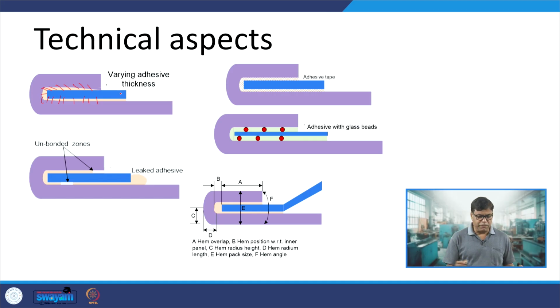And normally, when hemming is done, the adhesive thickness is difficult to control. In hem flange bonding, it is difficult to control the thickness of adhesive, because somewhere it is thin and somewhere it is thick. So, this reduces the mechanical performance. Therefore, a few approaches have been developed, like use of adhesive tape, so that the thickness will be uniform wherever the bond is created, or adhesive with glass beads. So, this helps in controlling the thickness of the adhesive uniformly.